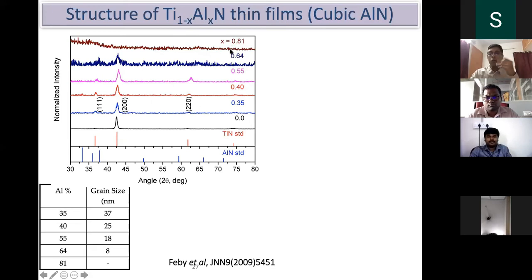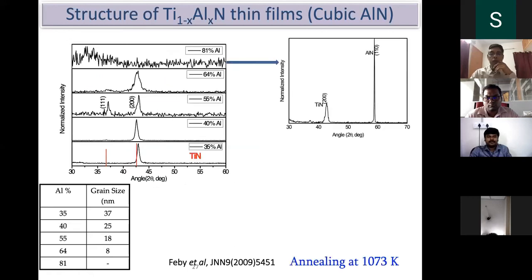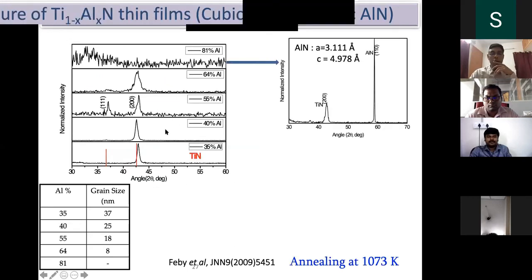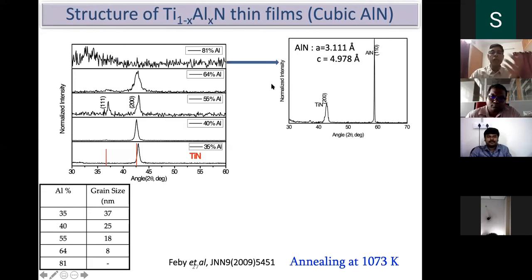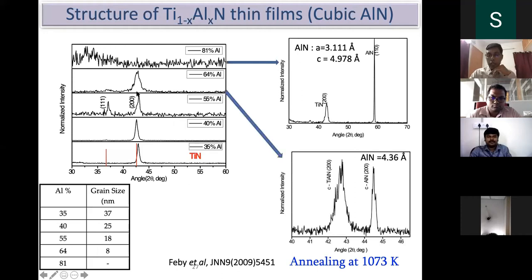So we wanted to know what happens when you anneal them. When you anneal them, this particular 81% aluminum, you can see two peaks formed. That is, one is for the hexagonal aluminum nitride and titanium nitride. And particularly when you anneal this 64%, only this peak splits into two. There is cubic aluminum nitride and cubic TiN. You can ask me a question, how this is a cubic aluminum nitride? I will tell you how.